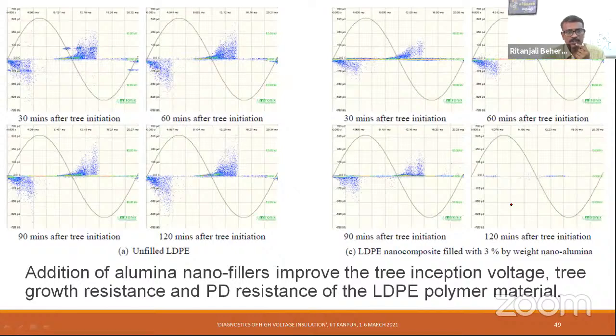This is another one which shows the PD phase-resolved patterns. The left one is for the unfilled LDPE. This is after the tree initiation. This is 30 minutes. After 60 minutes. And the third one is 90 minutes and 120 minutes. This is an unfilled epoxy. In the unfilled LDPE, sorry, not epoxy, LDPE.